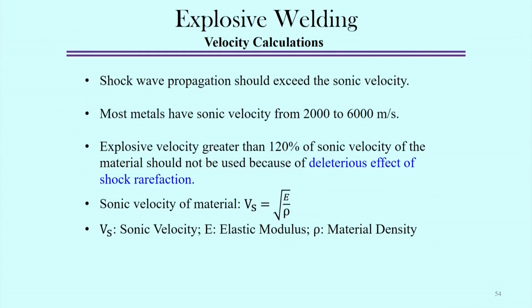So, velocity calculation can also be done. In the principle during the process, the shock wave propagation should exceed the sonic velocity, meaning the sound velocity within that medium, that means within that metal. So, the shock wave should propagate faster than the sound velocity. So, most metals have a sonic velocity from 2000 to 6000 meters per second, that is the data, and explosive velocity greater than 120% of the sonic velocity of the material also should not be used,